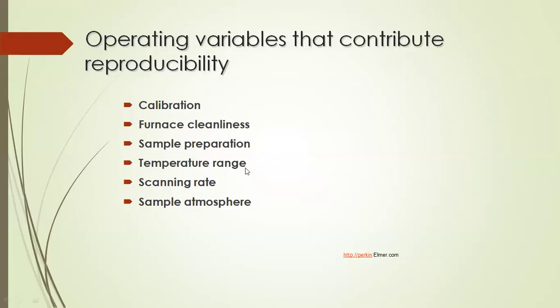Temperature range. Always select a proper temperature range for degradation. Otherwise, you will select a range which is lower than the degradation range of your sample, then you will not get degradation. You will get only a straight curve and your sample will not degrade in the range which you have selected. Scanning rate is important because I've shown you what will happen at 10 degrees centigrade and at 200 degrees centigrade. And sample atmosphere, which we will see now.